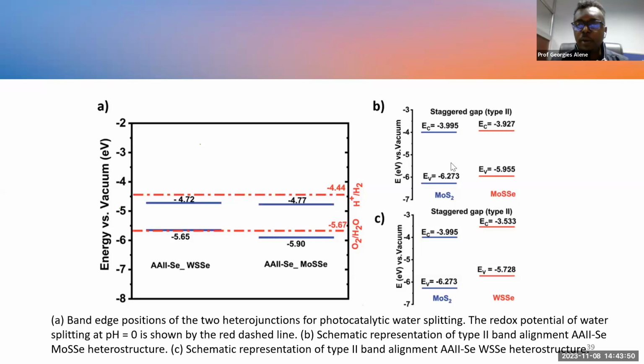And this type 2 band gap alignment is actually very good for photocatalytic activity because it is more efficient to separate the photo-generated carriers. The electrons will reside on one material and the holes will reside on the other material. So we can significantly reduce the recombination rate, and it is good for photocatalytic application. So this is interesting because we found type 2 alignment for both of them.